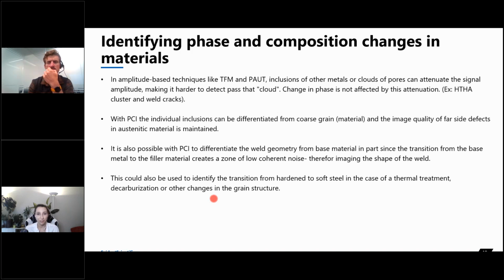It's also possible to differentiate the weld geometry from the base material. It doesn't work for everything, but we've seen it pretty frequently that there's a transition from the base material to the filler material, and we can see that in the zone of low coherent noise, and therefore it images the shape of the weld. So if the asset owner, after 40 years with the component in service, might not have the drawing for that weld anymore, sometimes it can be helpful. Sometimes you can see if it was a double V or a single V, so you have more information about that given weld.